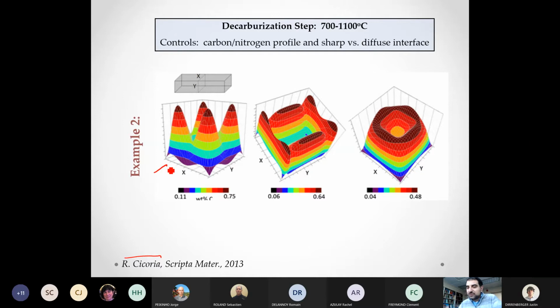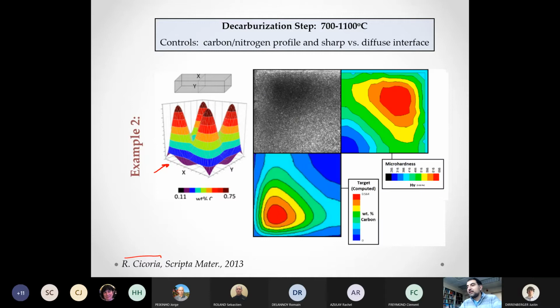So if we take this example here, where we have four regions of high carbon concentration in a matrix with lower carbon concentration, this is the desired profile that the user wanted. This here is the microstructure we got at the end of the heat treatment. It's a fine microstructure of martensite and ferrite, and the different shade just indicates more martensite when it's darker, less martensite when it's lighter. And this is the hardness map that we get. And you see the good agreement between the two. We can more or less get these interesting profiles that we want.